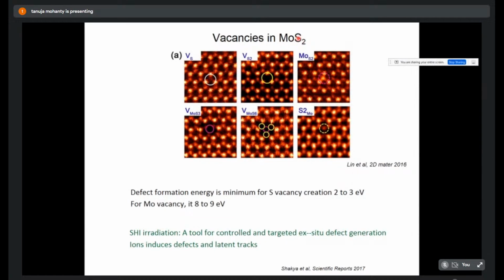So what can be the defects? One is the vacancy corresponding to S. Then the divacancy, where 2S are not there. Then MoS2, so one Mo and S2 as the vacancy. Then vacancy corresponding to MoS3, there can be 3, and the vacancy MoS6. So many vacancies can be produced, and normally the S vacancy requires 2 to 3 eV, and for the molybdenum vacancy 8 to 9 eV of energy is required to create this vacancy.